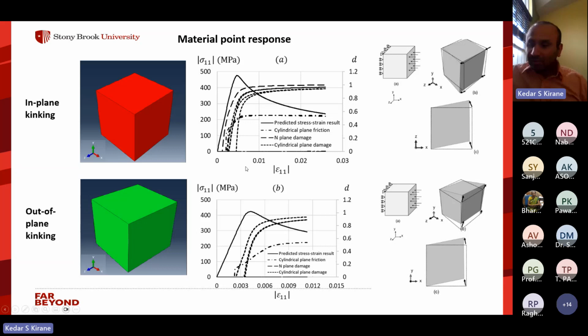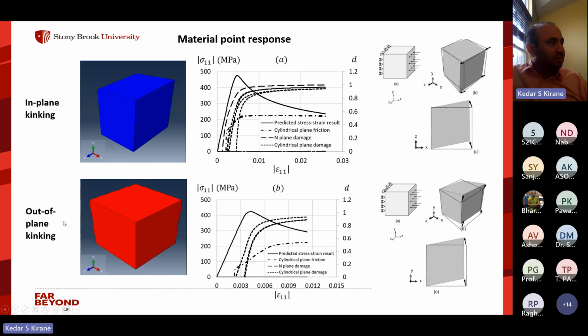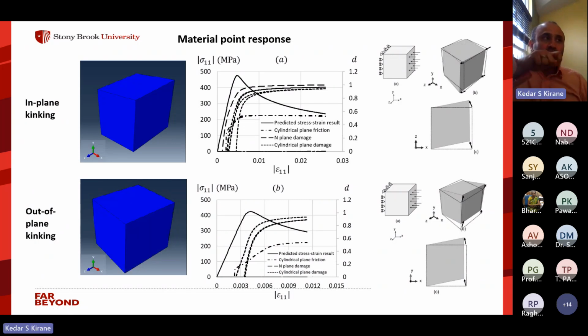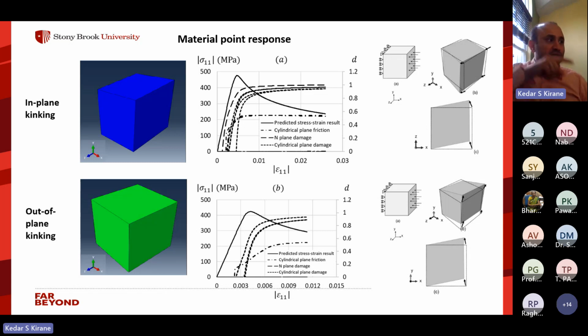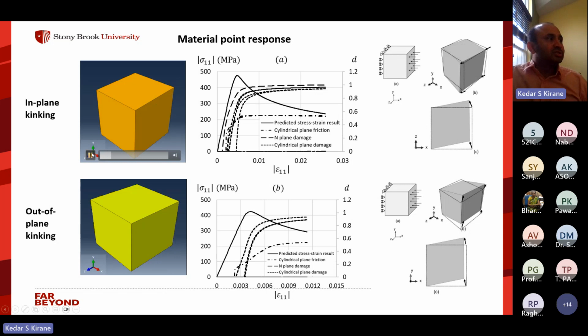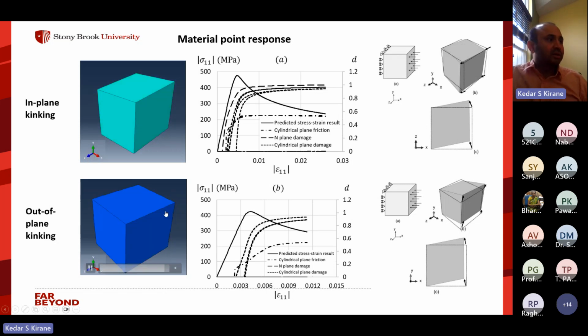So we implemented this as a user material subroutine in Abaqus. And these are some of the results. So this is initially single material point evaluation of the model. You can see maybe at the bottom first, we have the out of plane kinking version of the model. In this case, the load was applied as a uniaxial compression in the x direction. And you can see that the application of compression actually leads to local rotation. So compressive loading causes shear. And this is a result of only our constitutive framework embedded within it. Okay. Same thing can happen for in-plane kinking. The shear strain is like the 1-2 shear strain. And here it is 1-3.